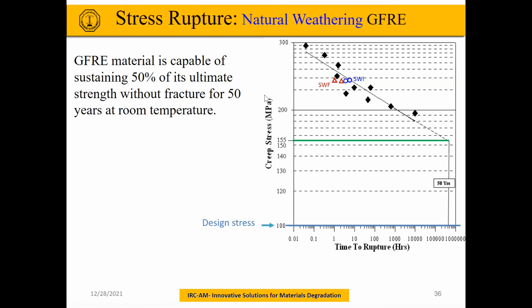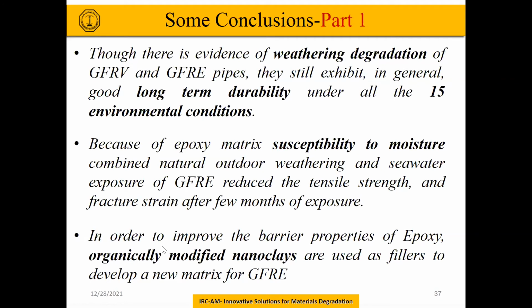of GFRE. Let me conclude this first part, part of the work that we have done for Saudi Aramco. Though there is evidence of weathering degradation of both GFRV and GFRE, they still exhibit long-term durability under the environmental conditions. What I have presented here is only a few of the results. Epoxy seems to be more susceptible to moisture, and its tensile strength and other properties degrade with exposure to water.